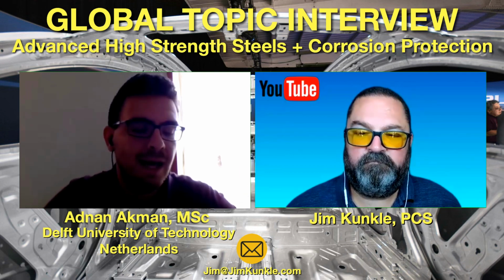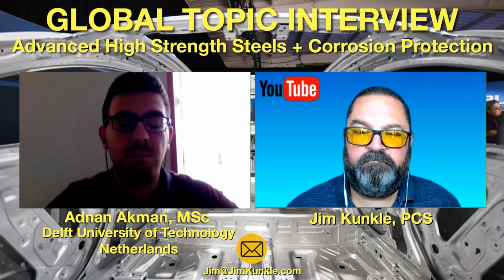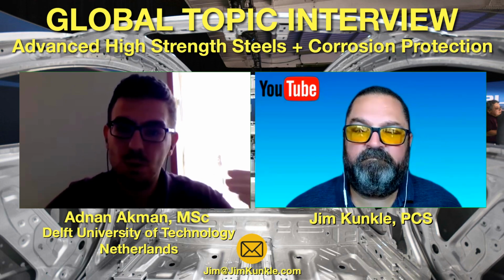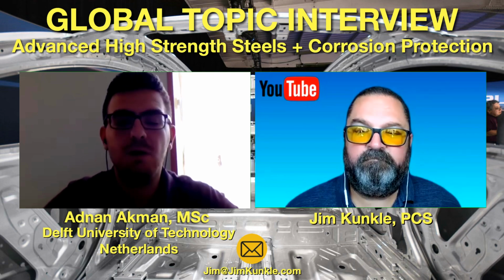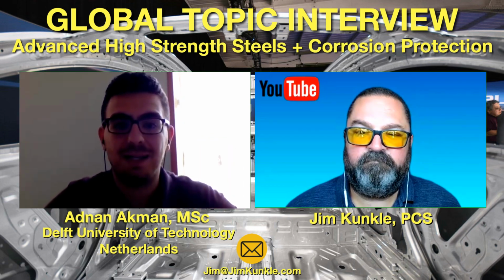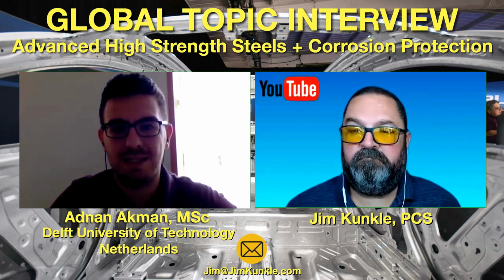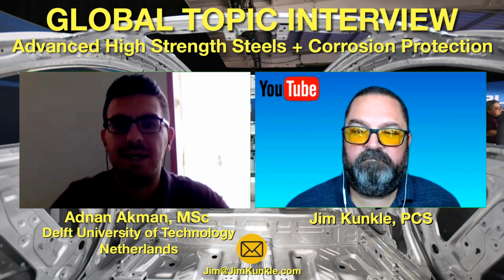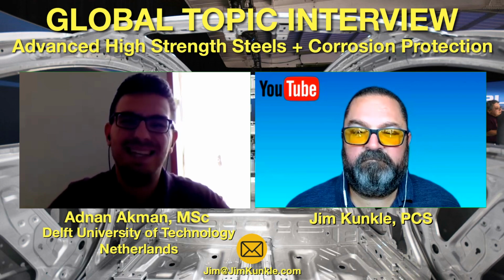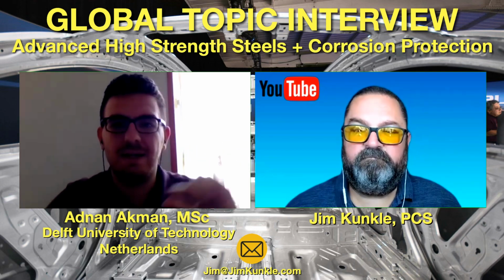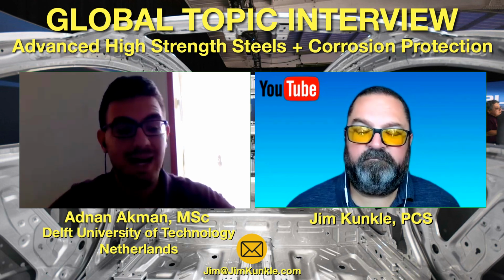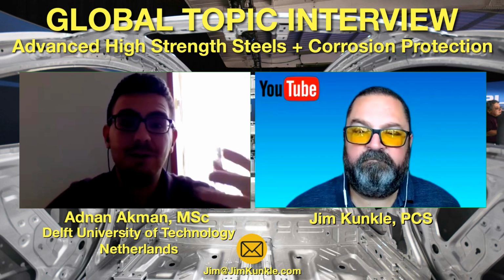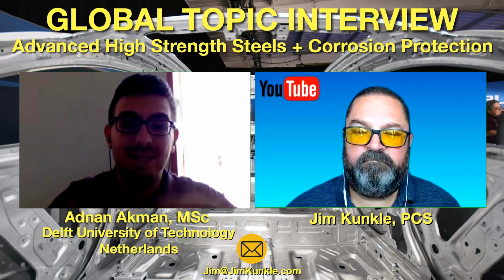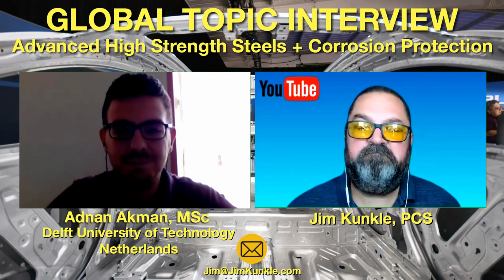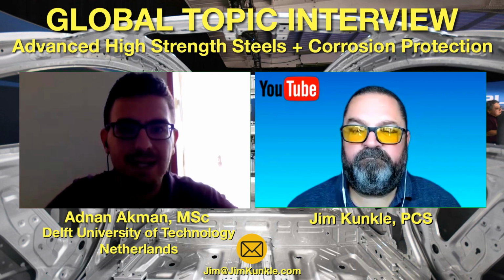With the application of current, zinc will transfer to the steel surface, and you have a zinc layer on top of your steel. If you compare these two techniques, the processing temperature in electrogalvanizing is quite low compared to hot dip galvanizing. Also, the coating in hot dip galvanizing is thicker compared to electrogalvanizing. For example, for outdoor applications, hot dip galvanizing is quite suitable due to the thick layer. In electrogalvanizing, the thickness is limited, thinner than hot dip galvanizing. And due to the thin layers, electrogalvanized coatings look better and smoother, aesthetically, compared to hot dip galvanizing. And the last one is hot dip galvannealing, also called galvannealing.